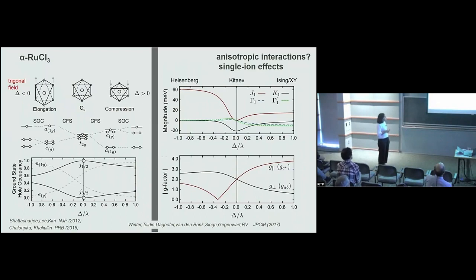So what we have in this case is indeed this perfect Kitaev interaction when we have a strong spin-orbit coupling. However, if the systems show some distortions, and one of the most common distortions in these materials is the trigonal distortion, so basically that either the octahedra are squeezed or elongated, then there are many more splittings in this T2g set of states, and the orbital degrees of freedom get quenched, and we go away from the Kitaev either to the Heisenberg limit or to the Ising limit.